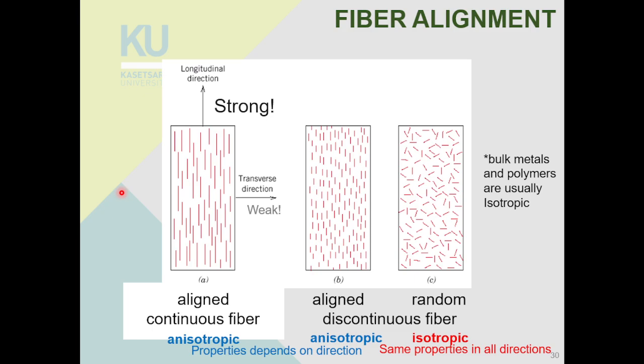So if you look at this aligned continuous fiber, aligned discontinuous fiber, and randomly aligned fiber, you can see that the aligned continuous fiber is very strong in the direction of the fiber, and very weak in the transverse direction, because the fibers do not help transfer the load at all. So it is very weak in this direction and very strong in this direction. When you have different properties in two directions, we call that material an anisotropic material, right?